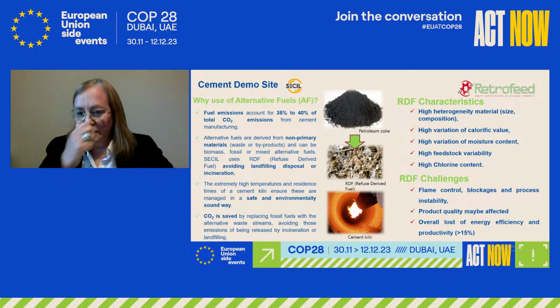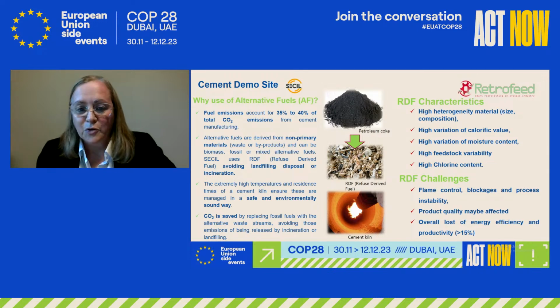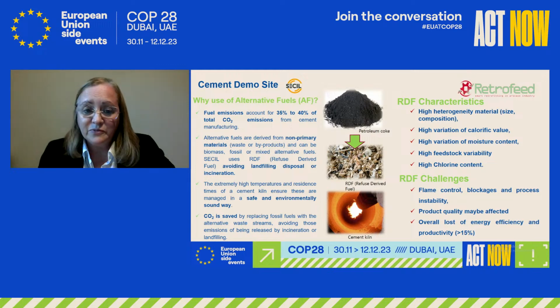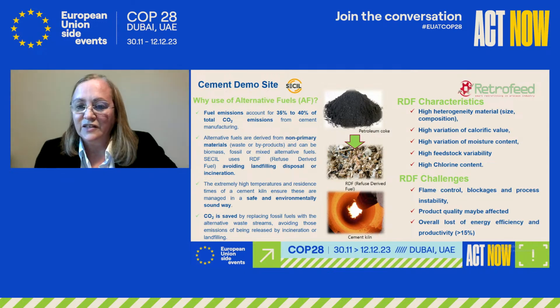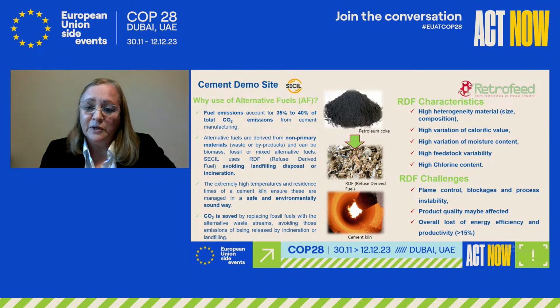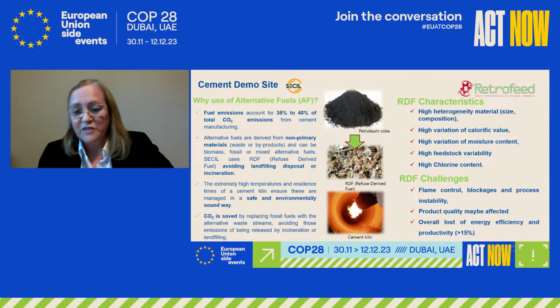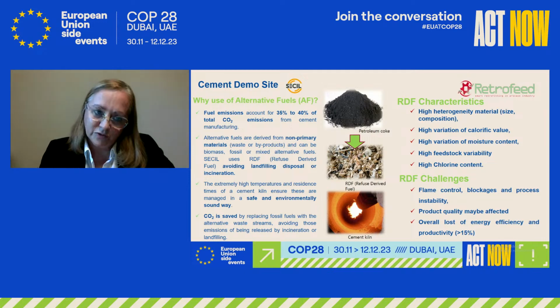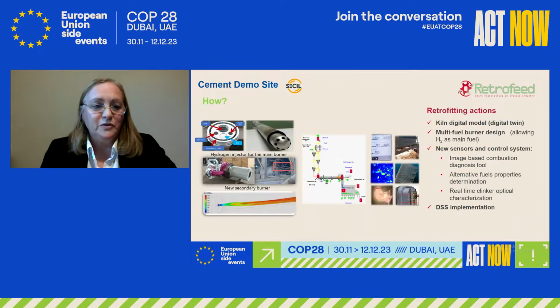So why do we want to use alternative fuels? First of all, we want to abolish the fossils, so we need another source of energy. These materials are waste materials, and by using them we avoid landfilling and disposal or dedicated incineration. But they have some characteristics that lead to challenges for using them in the cement kiln. Those characteristics are mainly the heterogeneity of the material, the variation of calorific value and moisture, the feedstock variability, and high chloride content. These lead to difficulties in terms of flame control, blockage, stoppage, and process instability. Sometimes it affects our clinker quality, and there is a loss of energy efficiency and productivity that can reach about 15%. So next slide, please.